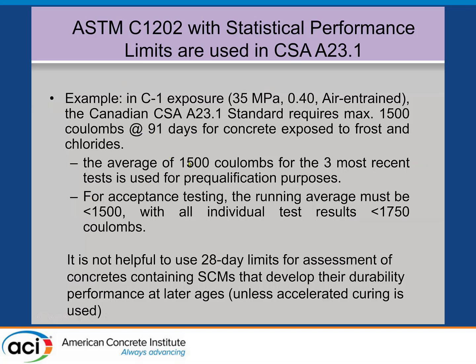And for the purpose of 1,500, we say that this is, if you're going to use it for acceptance, but we say it's the average of 1,500 coulombs for the three most recent test values can be used for pre-qualification purposes to qualify a mix. So you don't have to make new data, you can take the three most recent values. Say if we've been doing this mix, we get to 1,500. For acceptance, then we say the running average must be less than 1,500, with all individual test results less than 1,750 to allow for the variability of the test method. We know there's variability in the test method, and we don't want to start rejecting concrete because one value is high.